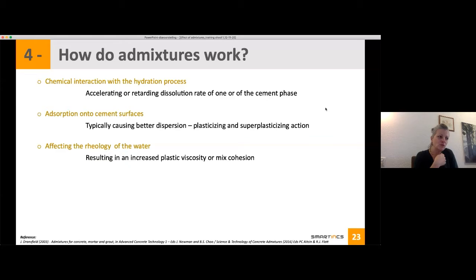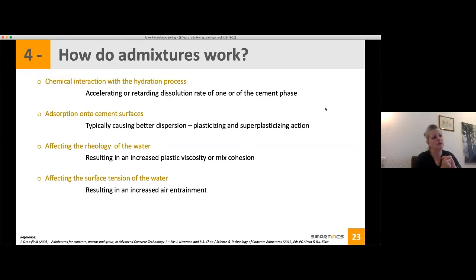Then you can also find a way to affect the rheology of your water. You will use this type of admixture if you want an increase in the plastic viscosity, or if you want to create more cohesion in your concrete mix. Another way is, if you affect the surface tension of your water, then you can stabilize the air bubbles that you have in your concrete, and that's typically how we will use air entraining admixture.